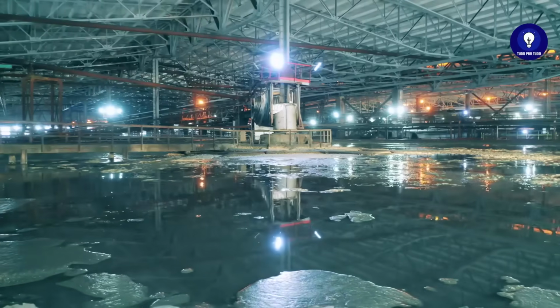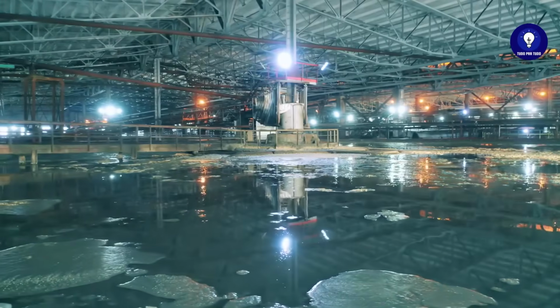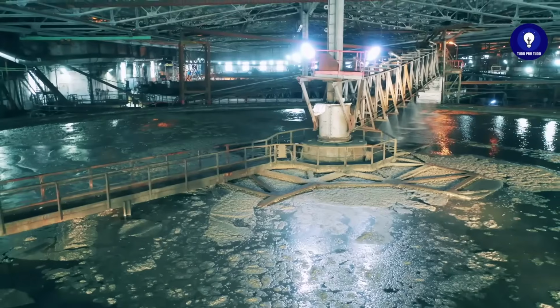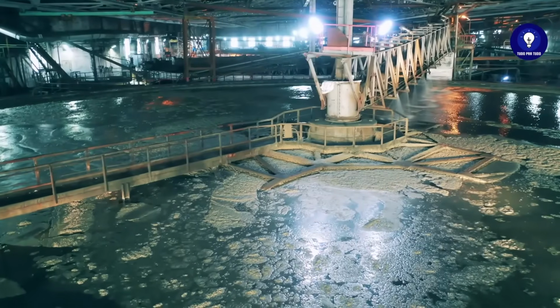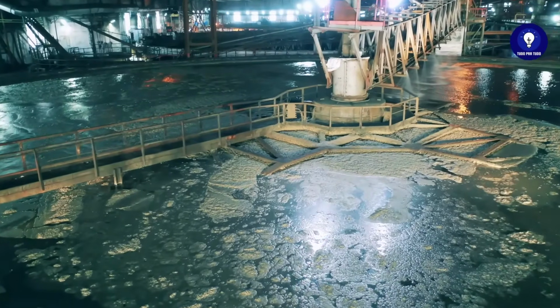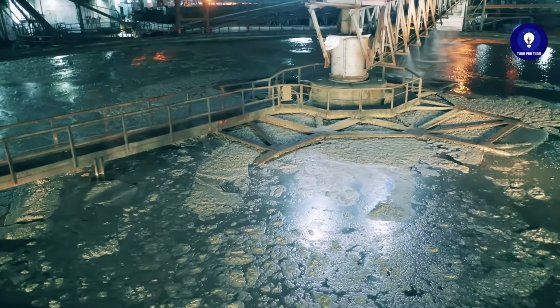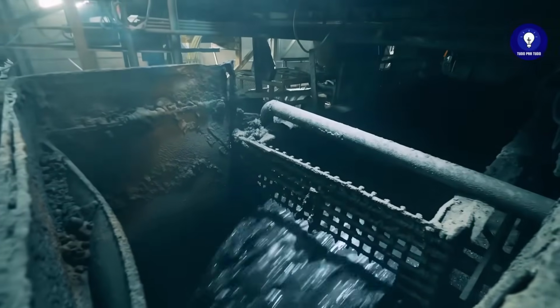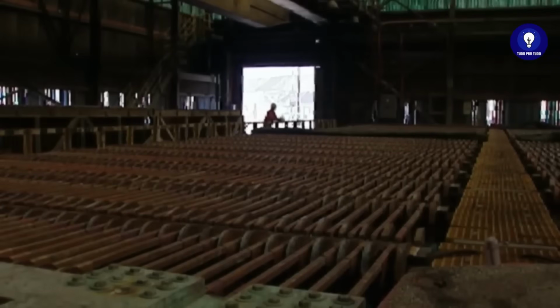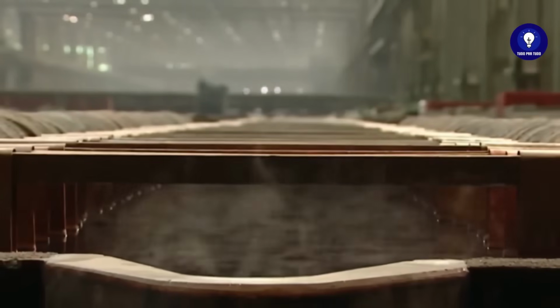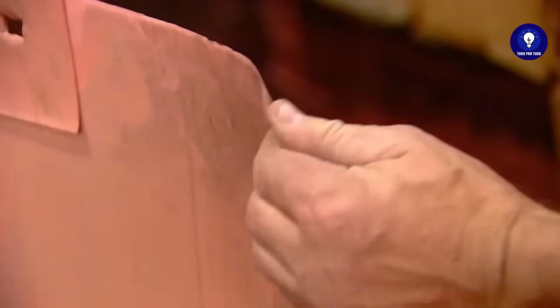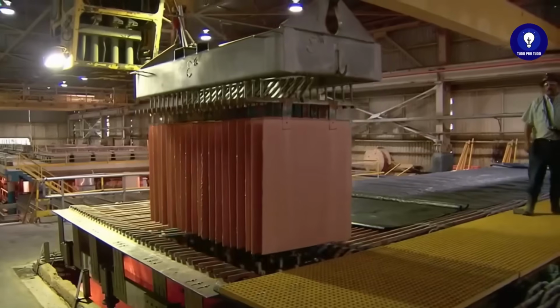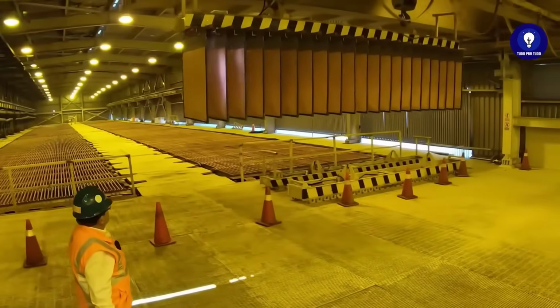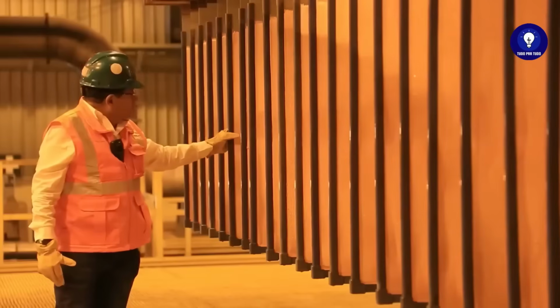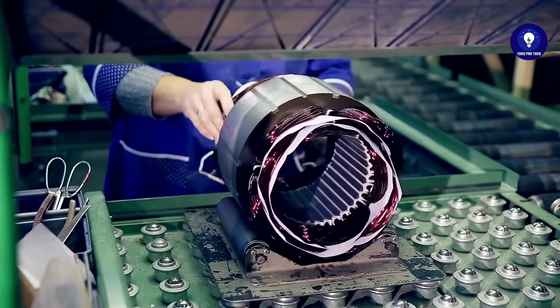In a special channel, the copper solution binds to an organic reagent and floats to the surface. Next, an acidic solution is added that increases the concentration of copper and makes it electrically conductive. The solution is transferred to a series of tanks with thin copper plates called cathodes. An electric current is applied, and the copper ions begin to deposit on the plates. In just 10 days, each one reaches a thickness of 2.5 centimeters. The purity reaches almost 100%, which is essential if the copper is to be used to manufacture electrical products.